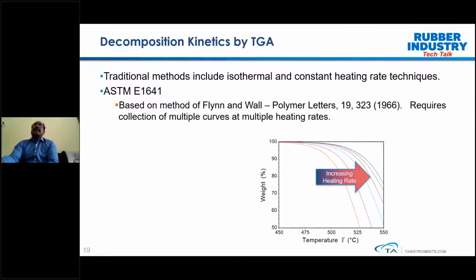Another is about the decomposition kinetics. So if you want to understand how the decomposition kinetics happens for a particular rubber material, basically this is the ASTM technique. Pretty much all the TGA can do that. The principle is the Flynn-Wall technique, where we would be doing the study at different heating rates. And as I told you, the decomposition is kinetic, so it always depends on the heating rate and the time. So if you are doing it at a slower heating rate, the material will decompose at a lower temperature. At a faster heating rate, you can see clearly the decomposition will shift to a higher temperature, and that is because of the kinetics involved.